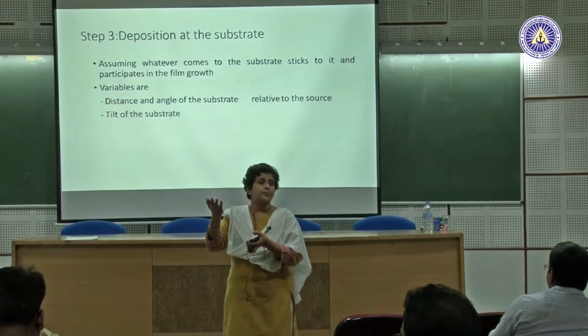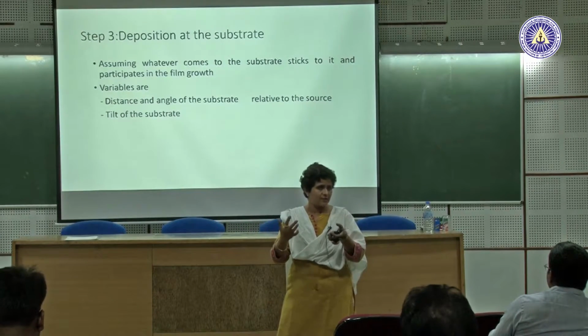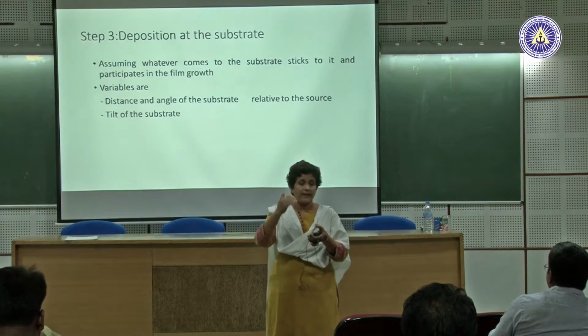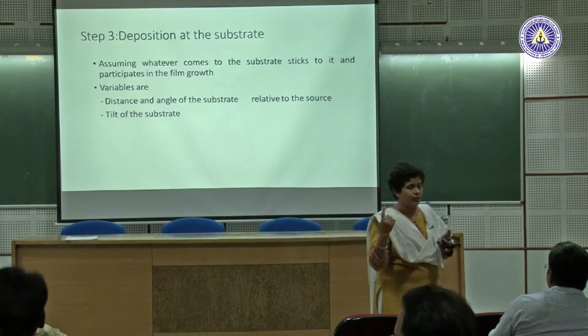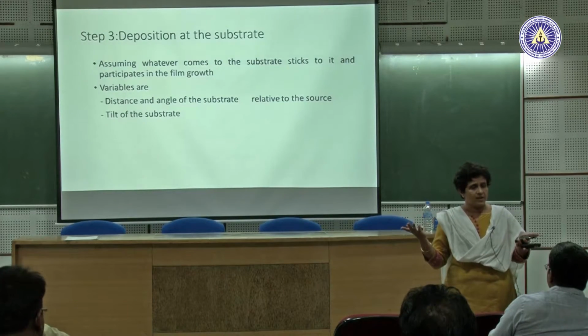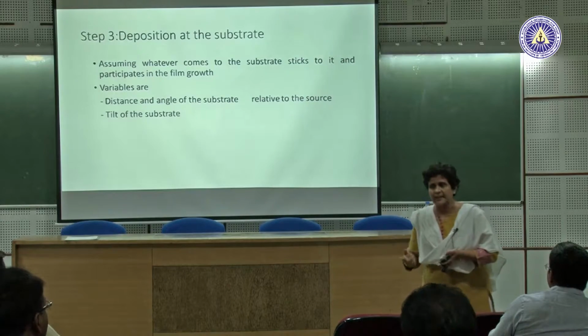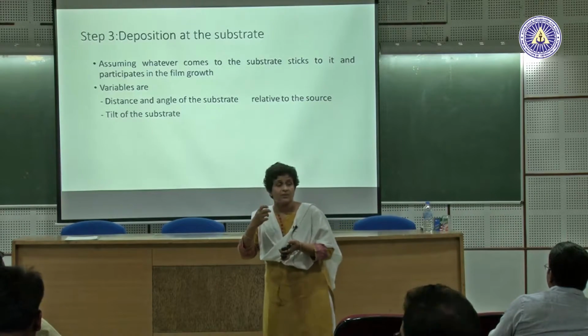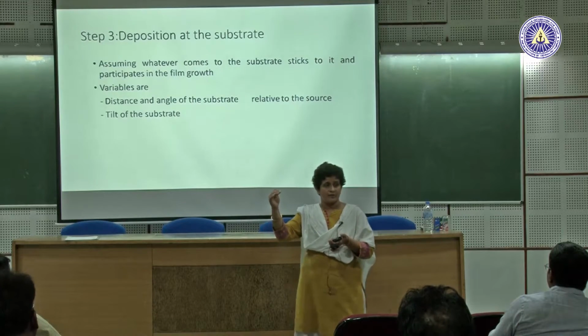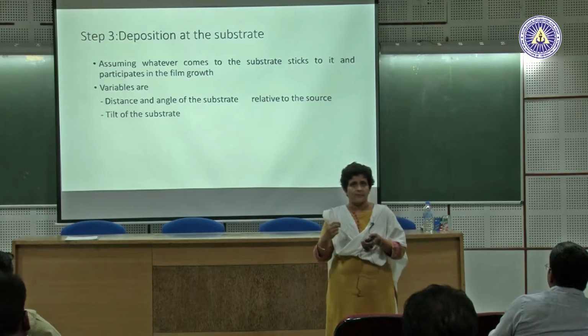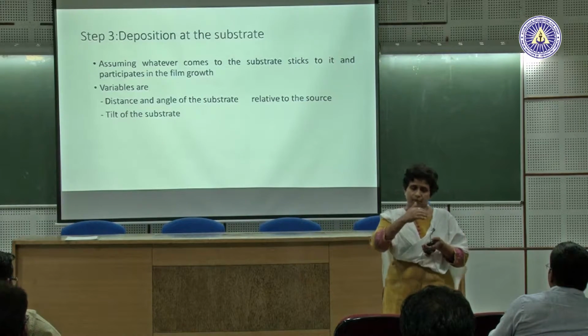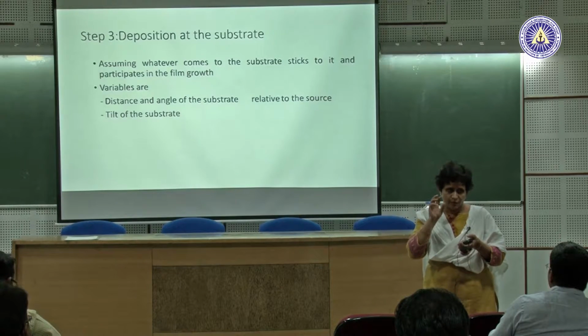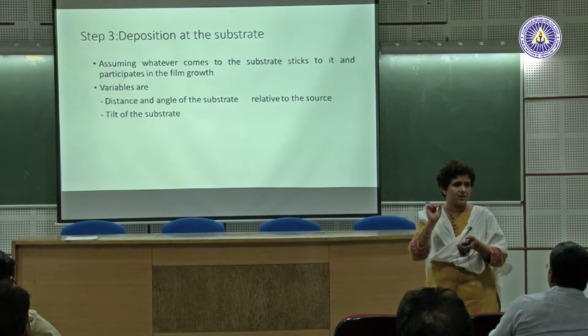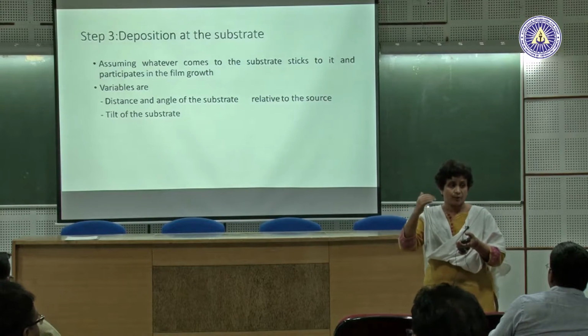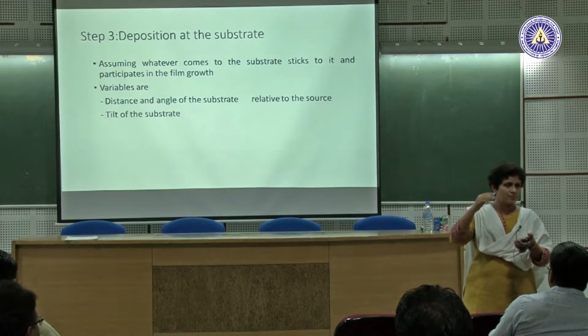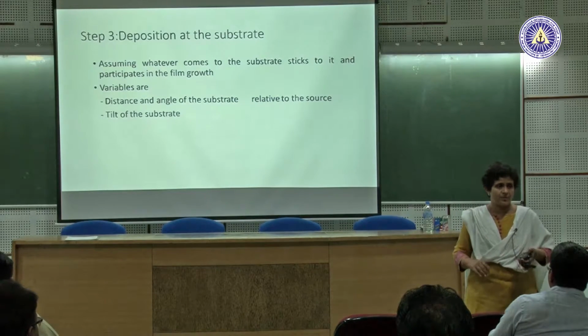Now, let us say I am depositing silicon oxide. I bring silicon and oxygen atoms together and they will be deposited on this surface. The bonding in this particular case between silicon and silicon oxide is going to be the bonding which is there in silicon oxide, the covalent bonding. So, if the cleanliness of the surface is maintained, the silicon which is coming with the thermal energy and getting deposited on the surface will form a covalent bond. If you bring in an atom which is not reactive, then it would be van der Waals or some other force. But if you are keeping the cleanliness and the atom is coming with enough energy, you do get regular bonding, good metallurgical bonding as you say it, between the substrate and the film. But it all depends on these parameters.